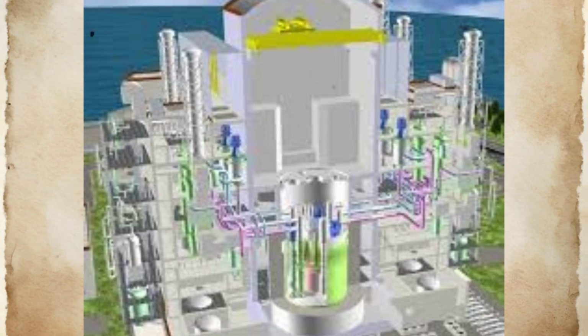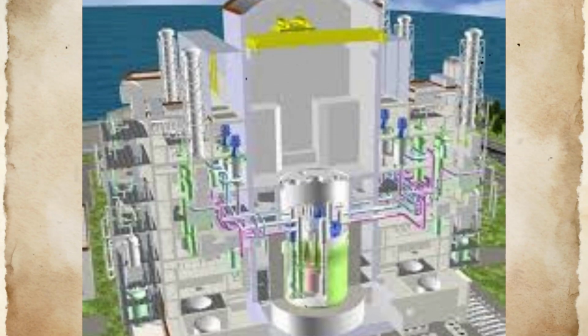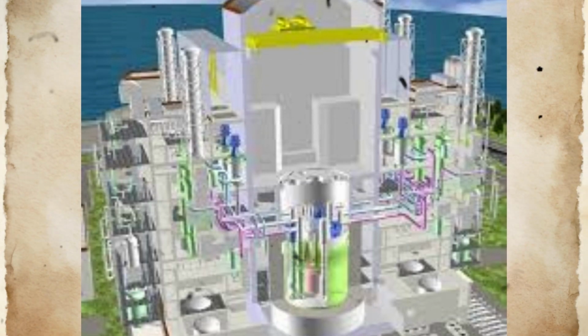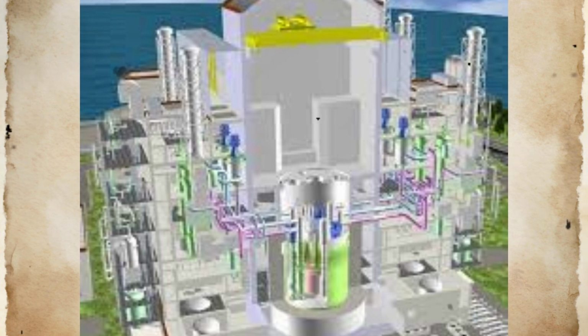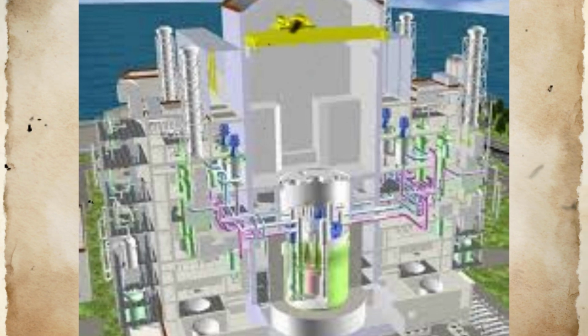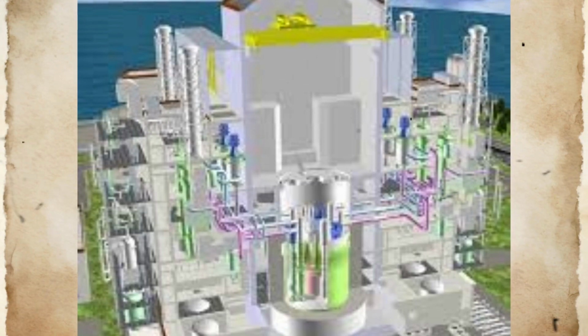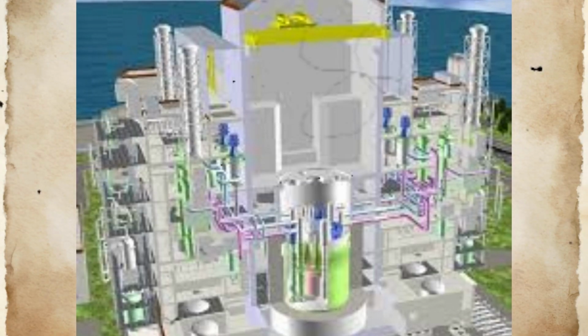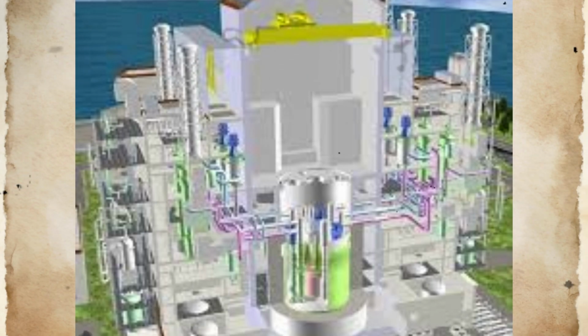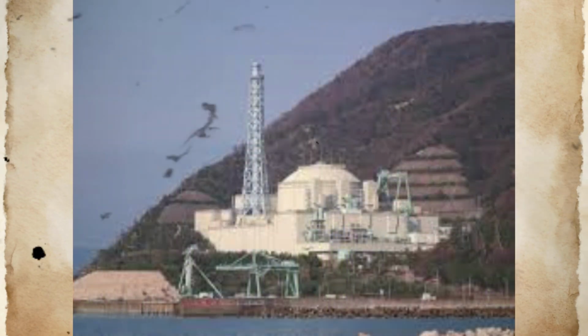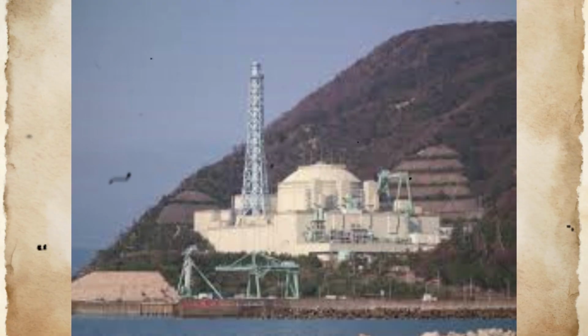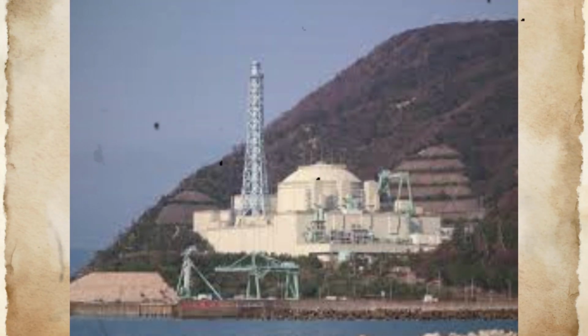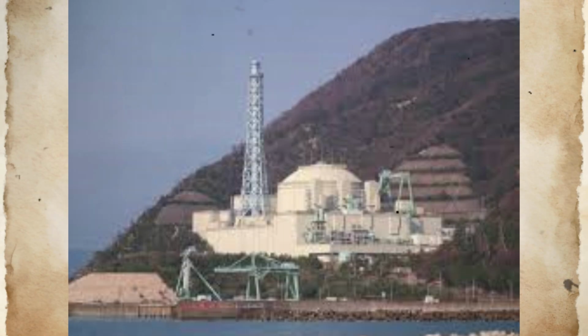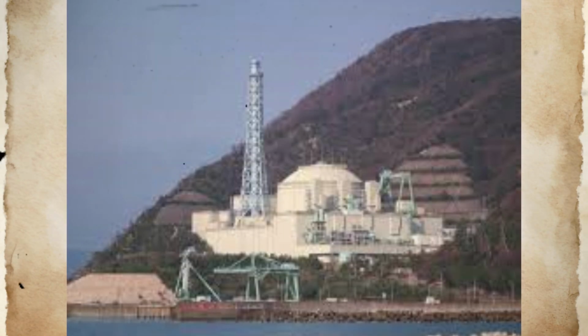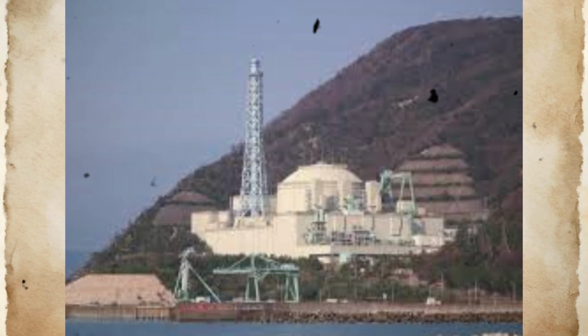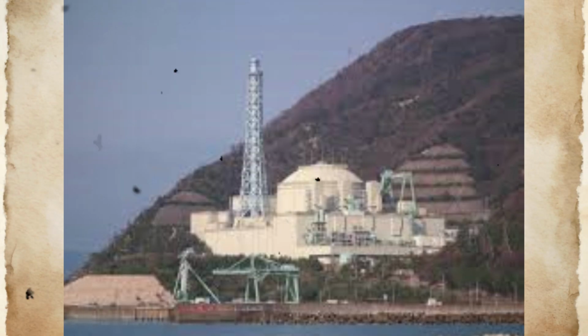The mass flow rate of escaped sodium was governed by fundamental fluid mechanics principles applied to the specific conditions present in SHTS Loop C. Secondary system pressure at the IHX outlet location was approximately 0.1 MPa above atmospheric pressure, providing the driving force for sodium ejection through the fractured well opening. The irregular geometry of the fatigue fracture surface created a complex flow path that influenced both flow rate and spray pattern of the escaping sodium.